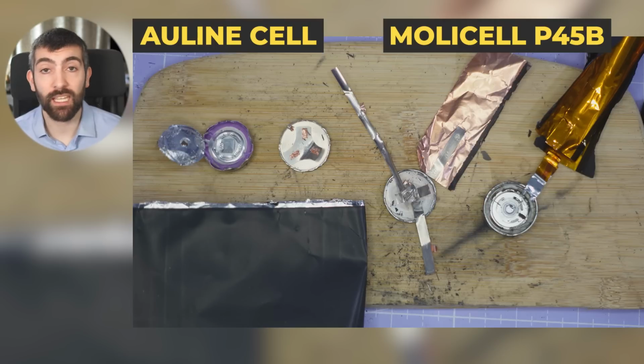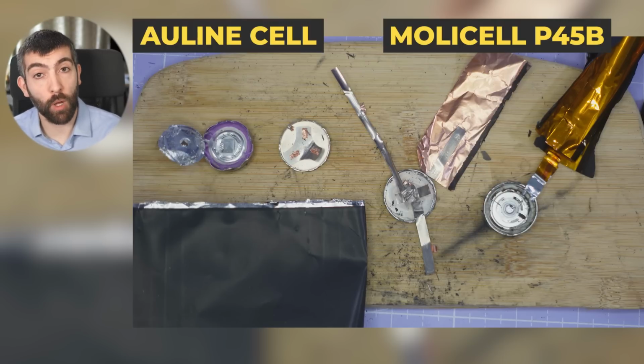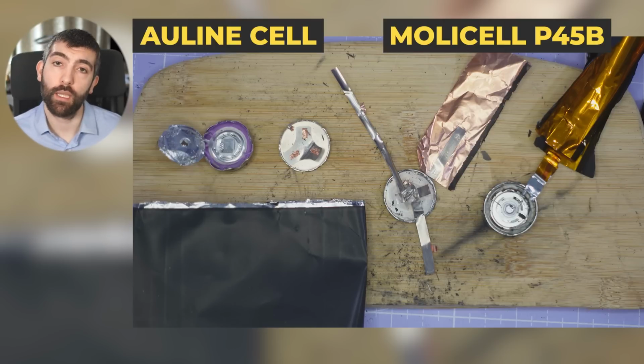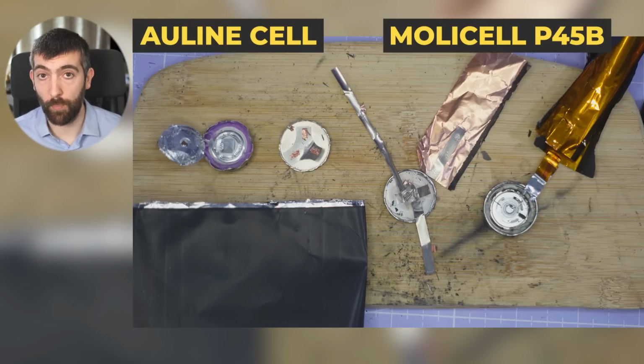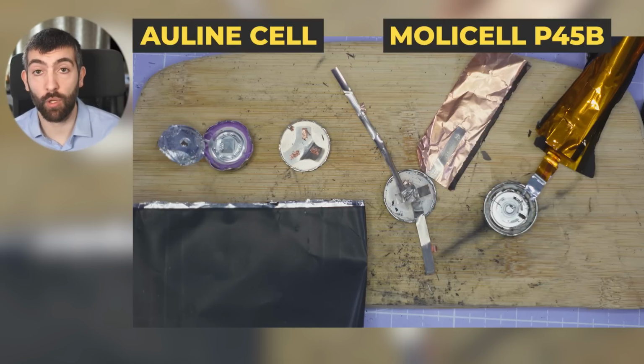The spot welds in the Molicell are also different to what we find in the Auline. The spot welds in the Molicell have a lot more individual welds that are smaller and much more closely spaced together. Compare that to the Auline welds, where we have a smaller number, maybe just half a dozen or so, of larger spot welds that are spaced further apart. I think that the Molicell method, where you have a much larger number of smaller welds, probably gives better contact